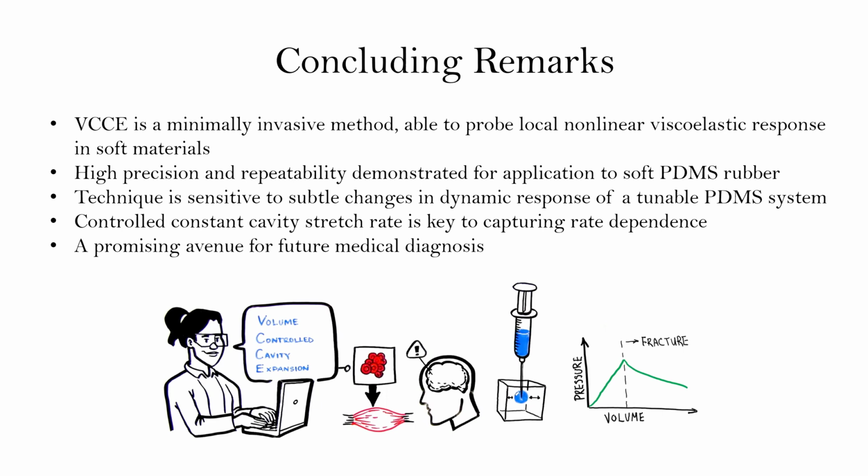That's a good question. I would say coming up with a loading protocol. Though we are presenting the final result, that took a lot of time, because first, we didn't realize that Mullins effect was playing such a big role. We also realized that we needed to go to a big cavity size and relax at that value and then do the experiments from there, because the more spherical the cavity is, the more reliable the experiments were.